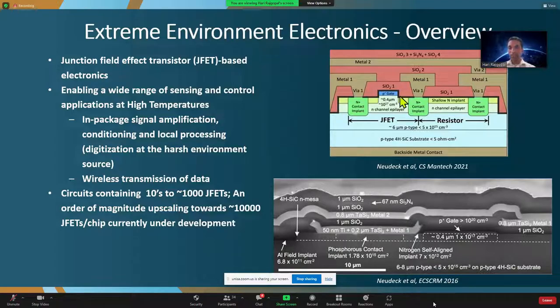And so the top is merely a schematic. It's a two-layer interconnect process. And since it's a JFET, it doesn't have an oxide layer like CMOS does. And the picture underneath is a cross-section scanning electron image. You see some pretty exotic materials like tantalum silicide, and then a pretty complex dielectric stack: silicon dioxide, silicon nitride, and once again, silicon dioxide. So these are the various steps that enable us to make something durable in Venus environments.